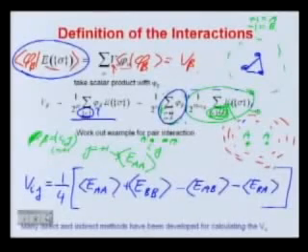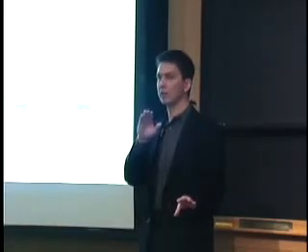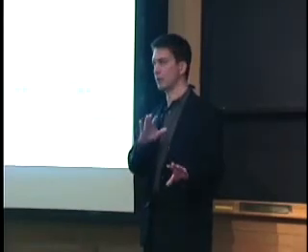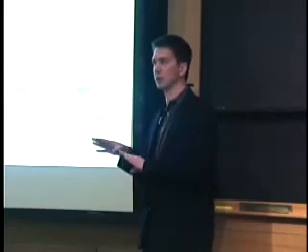The other thing is that indirect effects can be included. If you truncate your lattice model at pair terms, because it's an infinite expansion and at some point you'll have to truncate it, you are still including many-body quantum mechanical effects, because they enter in the calculation of the energy of these. So the level at which you truncate the cluster expansion, the lattice Hamiltonian, has no correspondence to the level of physics for your electron physics.